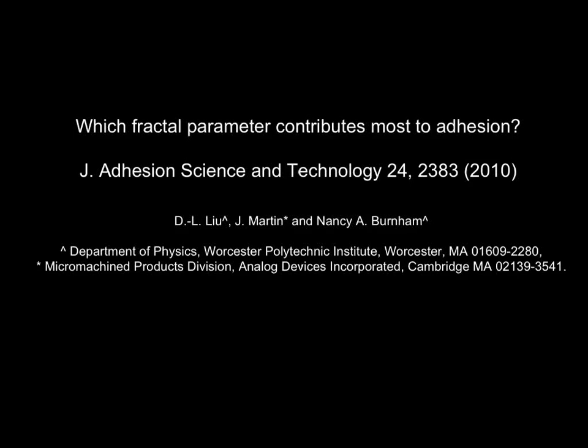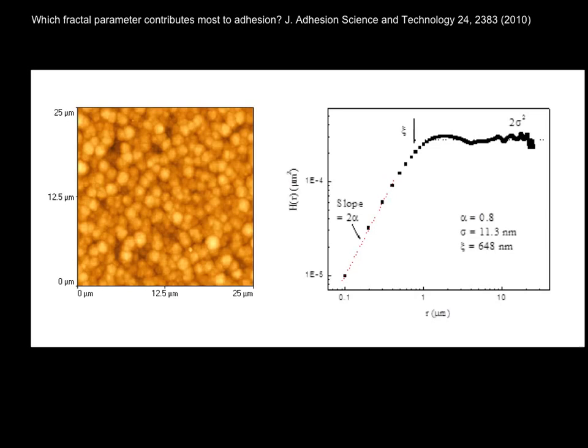This work was motivated by the desire to understand how the characteristics of surface topography contribute to adhesion. On the left, we have an atomic force microscope image. On the right, its height-height correlation function, from which you can determine three fractal parameters that characterize the surface topography.